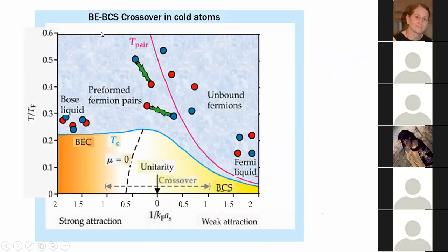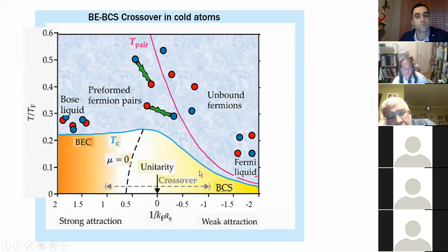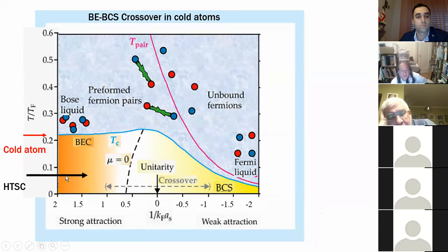And actually, this Bose-Einstein to BCS crossover has been studied afterwards very well by something called cold atoms. And in their plot, Bose-Einstein condensation takes place at just this idealized theoretical value in the case of cold atoms, but it is reduced by a factor of 4 in these cuprate superconductors. And in my opinion, this is because in the cuprate superconductors, there is a competing order. These cuprate systems are always competing with antiferromagnetic order. And on the other hand, cold atoms are so dilute that you don't have to compete with anything, and then this simple theoretical thing works.